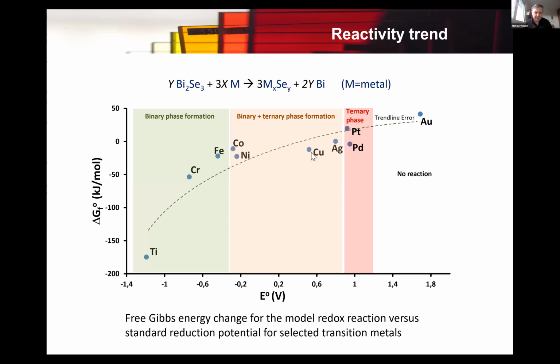Now, from all these studies and from the information for other elements, we can see that there is an obvious trend in the reaction with bismuth selenide. And I was already talking about the redox reaction. And when we are talking about the redox reaction, then of course we can correlate the intensity of reaction, or let's say free energy change, with the reduction potential of the metals. And you see that this pretty much correlates very well. While you don't get any reaction with gold, you get some ternary phases with platinum, palladium, and then you move through this mixed area into very reactive metals where you would get straight a binary phase.